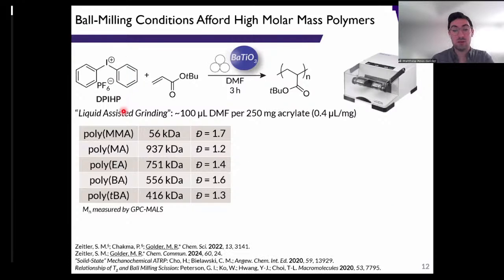So we eventually settled on these diaryl iodonium salts. These are aryl radical precursors, much like the aryl diazoniums, with a much better safety profile. And the idea here was that the exogenous mechanical force from mechanochemical ball milling would lead to reduction of the iodonium salt. The subsequent aryl radical could kick off polymerization, and we would end up with these polyacrylates or polymethacrylates.